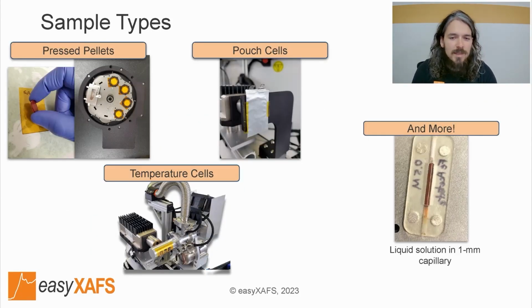In terms of how the samples are prepared, the most common method for solid samples is to grind a powder and mix with a binder to press into a pellet. So the pellets are typically sealed with Kapton tape and then mounted up in the instrument. So in this picture, you can see how we have a sample wheel with different positions that you can mount different samples in. And the sample pellets can be taped up or held on with these magnetic holders.